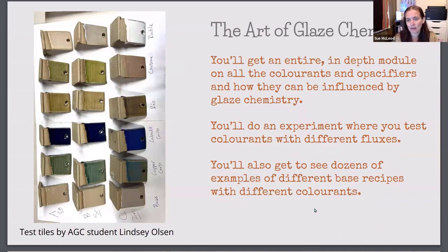In the Art of Glaze Chemistry, you get an entire in-depth module on all the colorants and opacifiers with examples of different concentrations and how they can be influenced by glaze chemistry. And you'll get an assignment to do an experiment where you test the same base glaze with different fluxes and different colorants. These are test tiles by Lindsay Olson. Here is her zinc base, her strontium base, and her calcium base. And then we've got copper, cobalt, iron, chrome, and rutile. You can see there's quite a difference, like the blue, for example: with strontium and calcium, you get this navy blue. As soon as you switch to zinc, it's much more vibrant, kind of an electric blue color when you're using zinc as your RO flux.